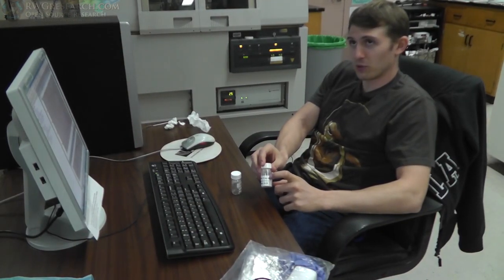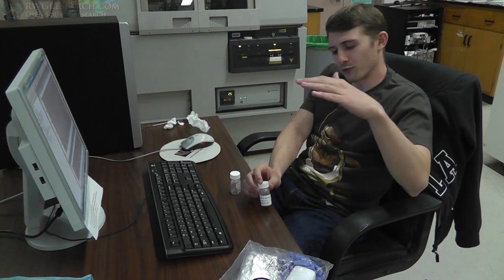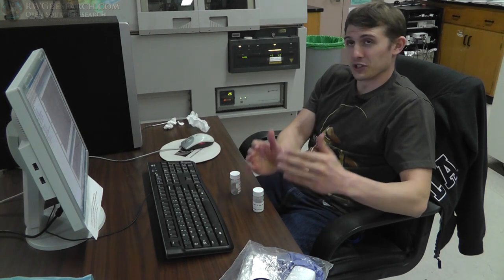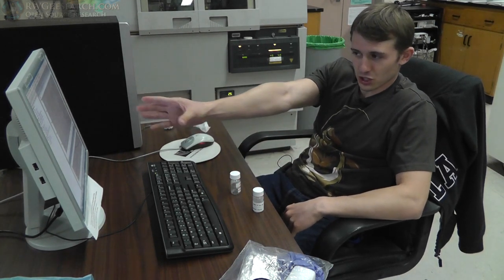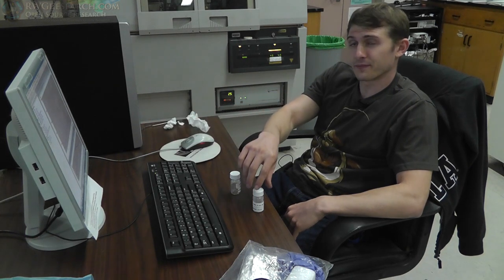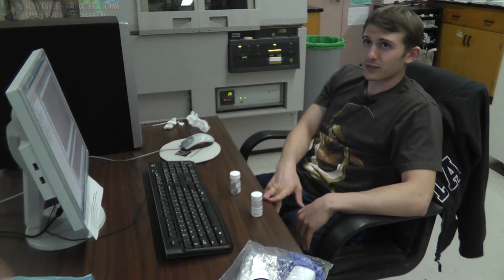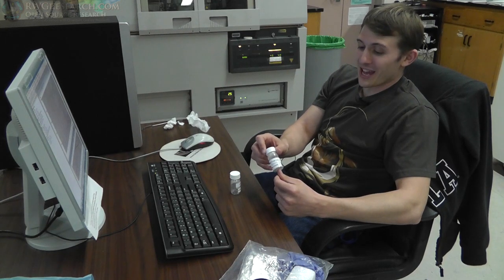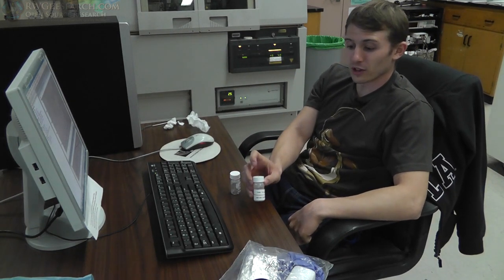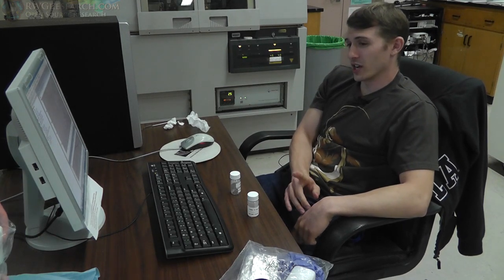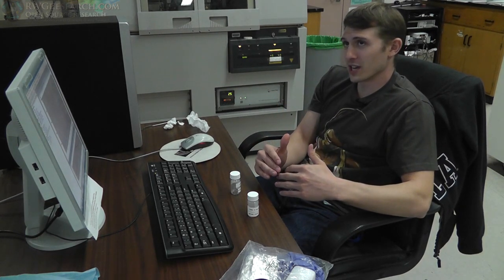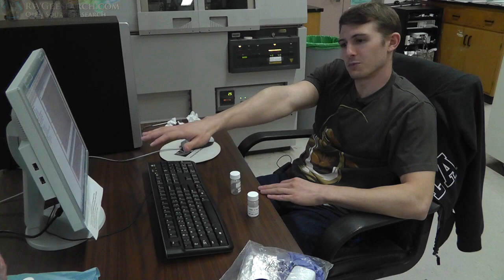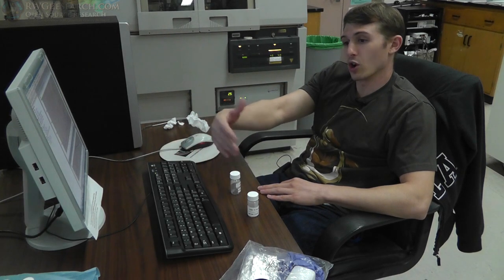So if there is palladium in this sample, you'll either see it in the form of palladium atoms forming a palladium structure, which would mean that it's not actually in your zeolite. Or if it's in the zeolite, then you'll see it like splitting certain peaks in your zeolite pattern. What if it's both? What if it's on the external and the internal? You'll see both. Because I washed it really good, but that doesn't mean anything. We'll find out. And it's got the organics now. So how is that? You'll see that too. Okay. Which if the, well, you'll see it if the organics are in a lattice. If the organics are not in a lattice, I should say, of their own, then you won't see them as an organic lattice. But what you'll see is once again, like splitting of various peaks because they're taking up space in what is an already existing lattice. Okay.